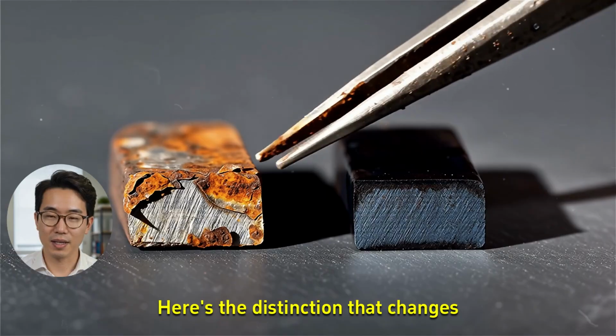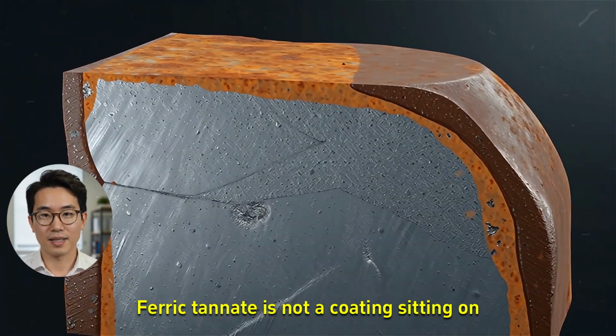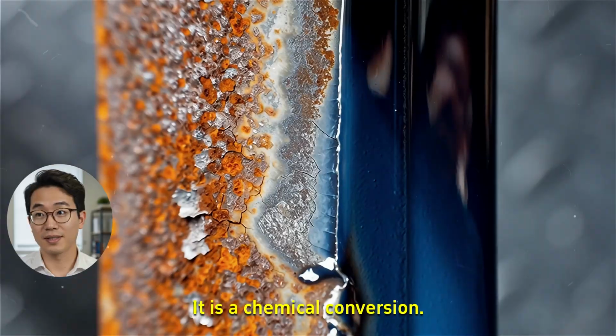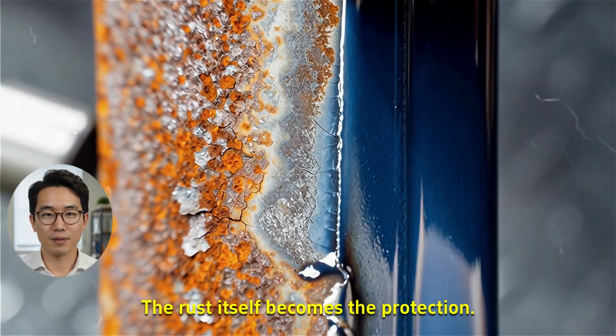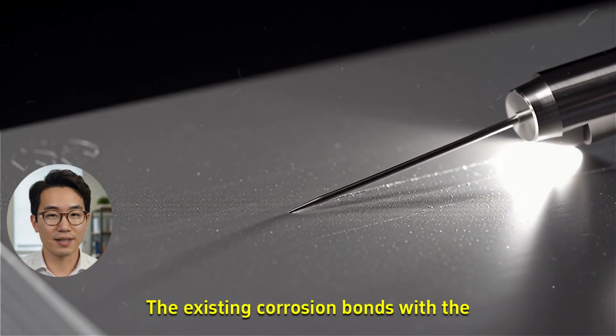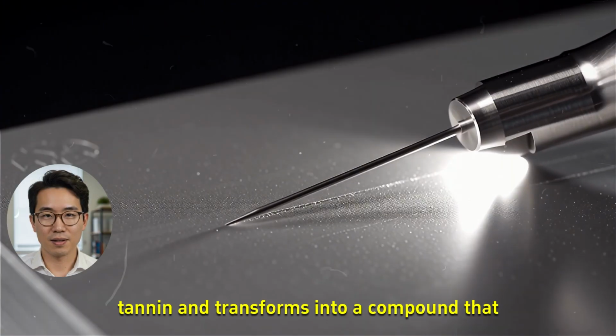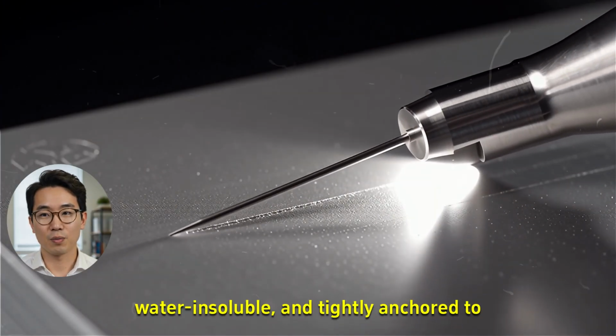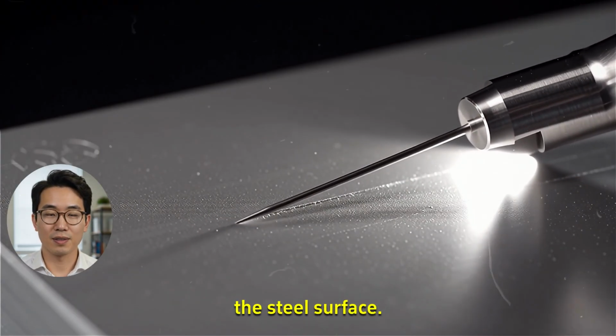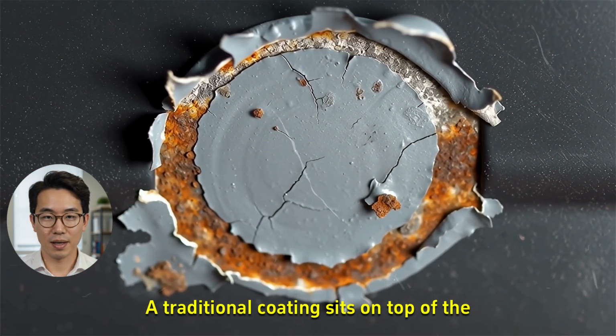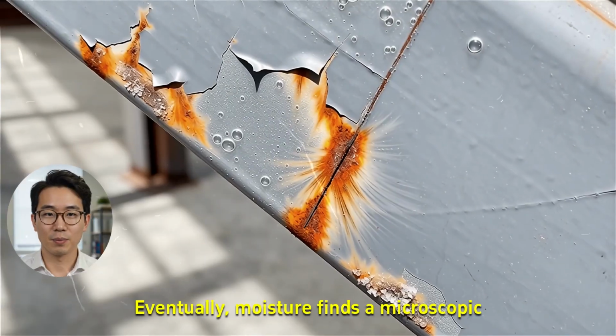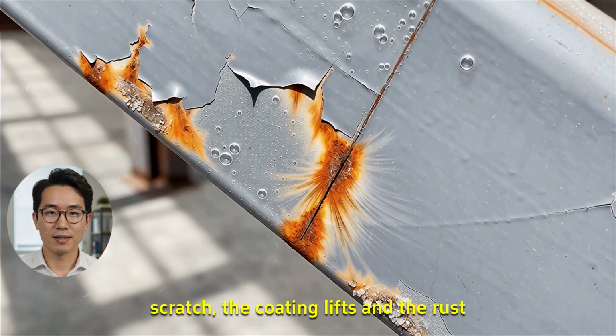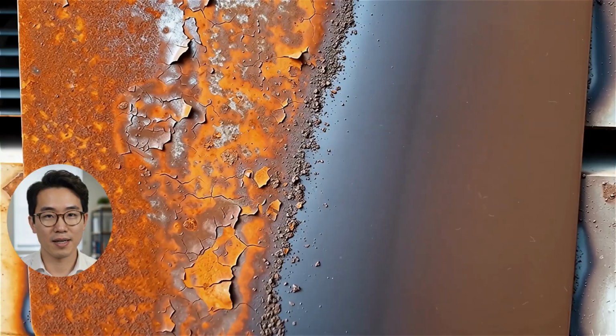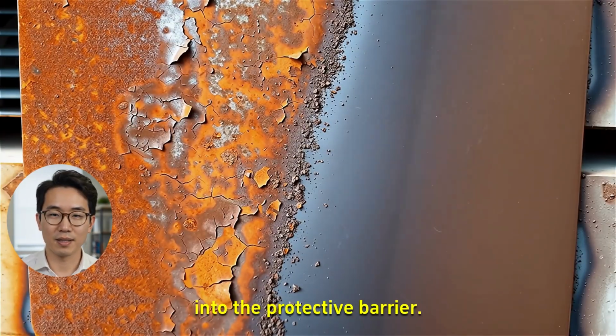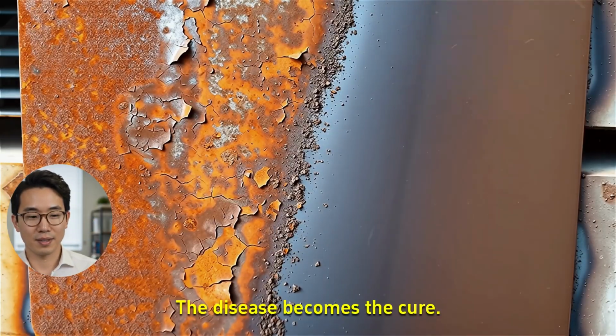Here's the distinction that changes everything. Ferric tannate is not a coating sitting on top of the rust. It is a chemical conversion. The rust itself becomes the protection. The existing corrosion bonds with the tannin and transforms into a compound that is hard, water-insoluble, and tightly anchored to the steel surface. A traditional coating sits on top of the metal like a bandage. Eventually, moisture finds a microscopic scratch, the coating lifts, and the rust returns. A conversion transforms the rust itself into the protective barrier. The disease becomes the cure.